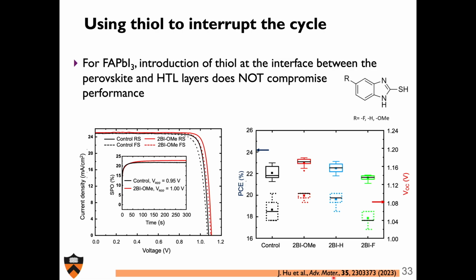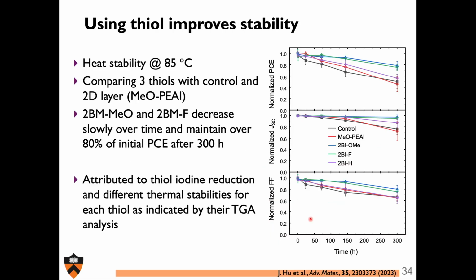It doesn't appear to compromise the performance of the systems, which is good. It might improve it, but statistically, let's just say it doesn't hurt it, which is already a good thing. And this is really just a vanishingly thin coating of this thiol compound, which we only tried three of them, whether this R group is methoxy or hydrogen or fluorine. It appears to preserve the performance of these devices, which is great.